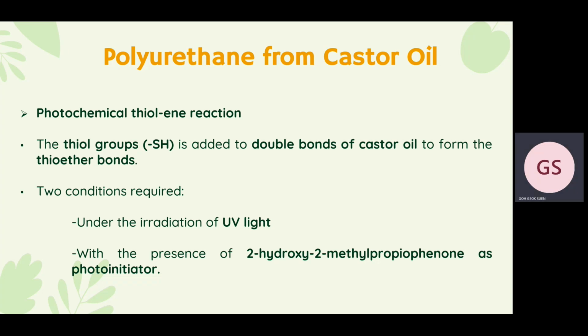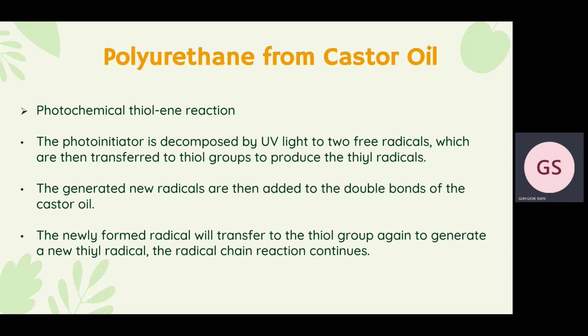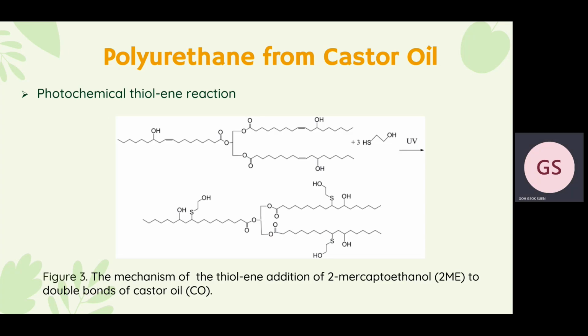The photoinitiator will be decomposed into two free radicals by the UV light, and the two free radicals will then transfer to the thiol groups to produce other new radicals. The new radicals produced will be added to the double bonds of the castor oil, and such radical chain reaction will continue to happen as the newly formed radical will transfer again to the thiol group to generate the new radical. And the mechanism of the first method is shown in this figure.